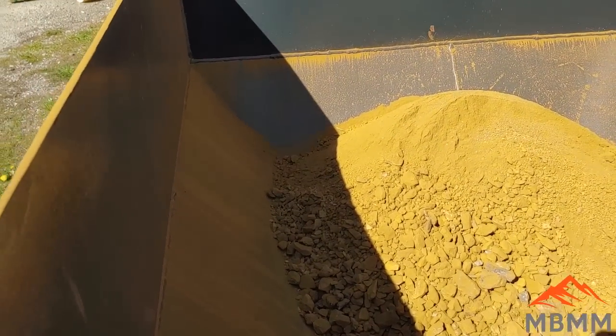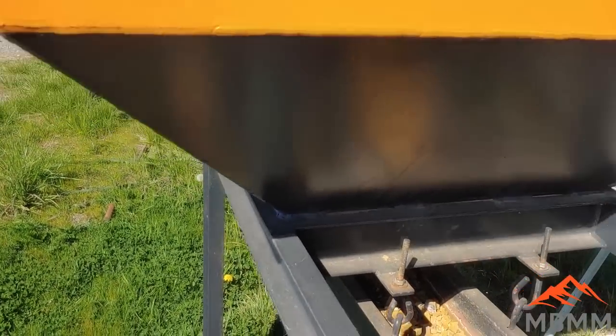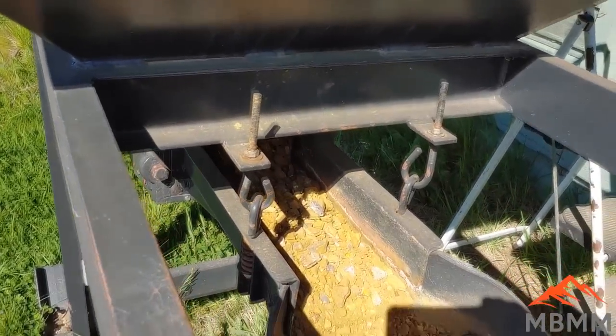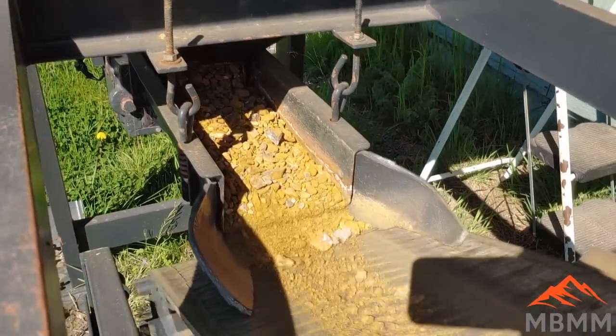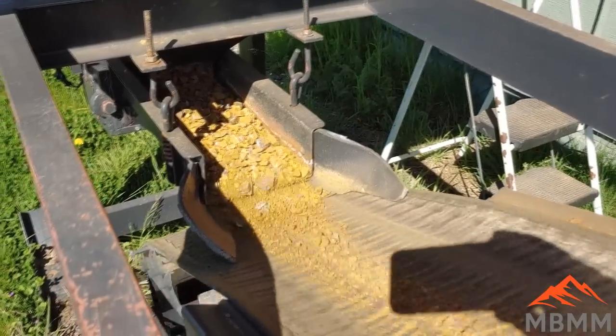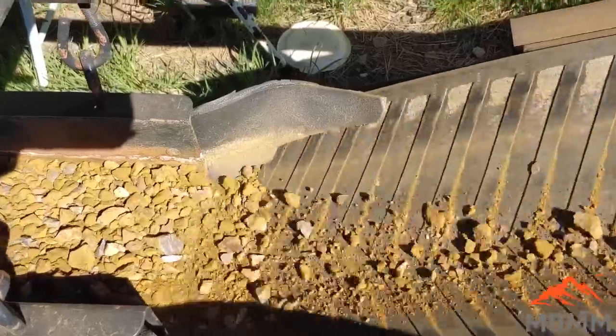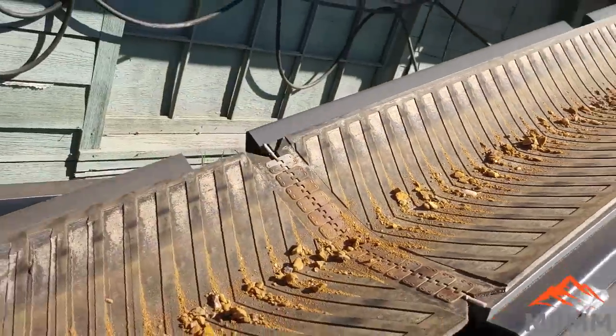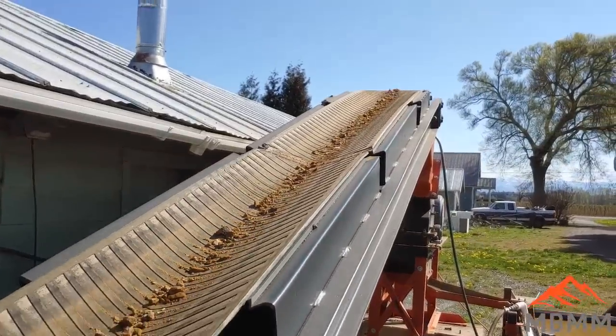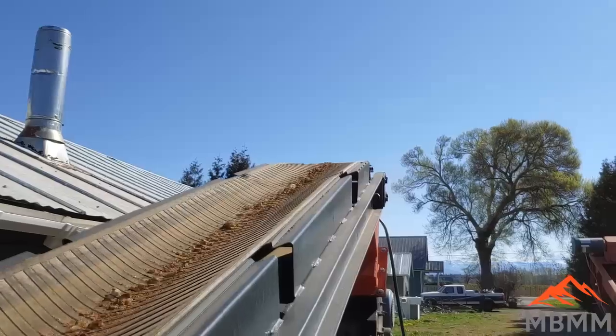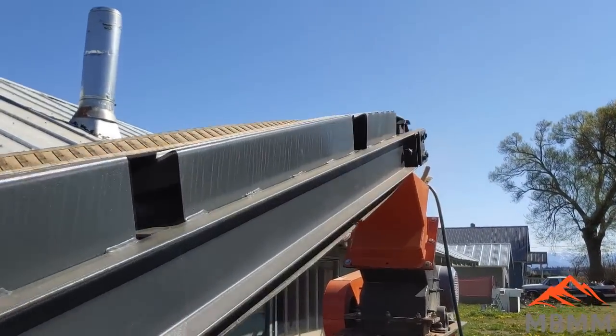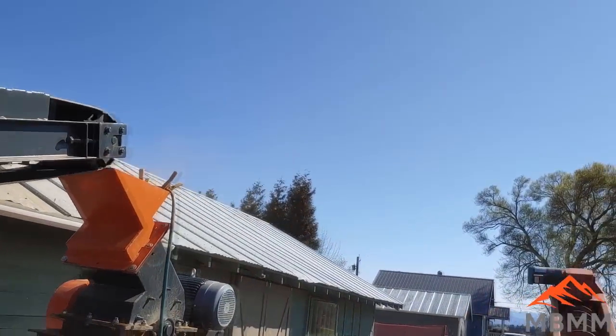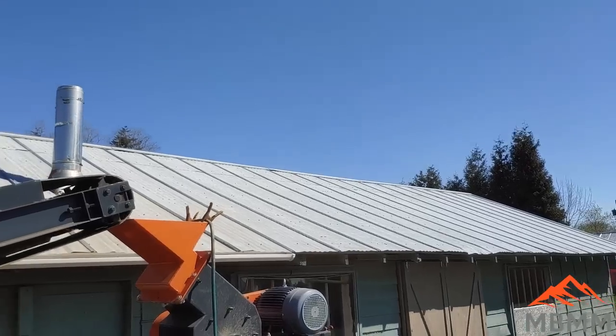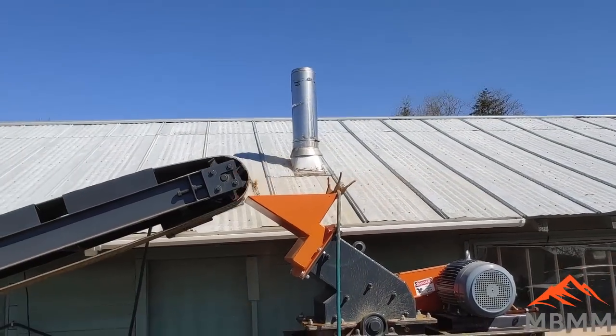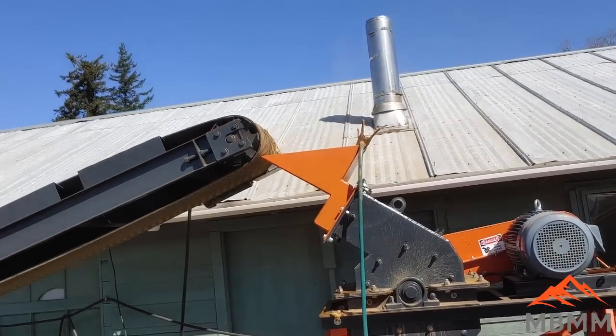One of our strategies for developing a mine site or processing old dump piles is to start out with a bulk sampling type program where you can get some equipment on site and do bulk sampling in the tens or hundreds of tons through the jaw crusher, the hammer mill, and onto the shaker table. You're going to learn a lot of information about the amount of gold you have, the percent recovery, the values in your ore, the grind size, and then once you have all that information, you can make a really good educated decision about how to improve the system that you have.